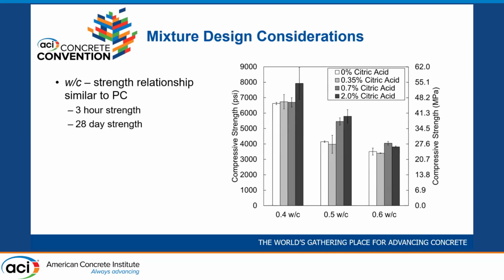And at 28 days, these are the strengths. So the strength continues to develop well on after 3 hours. And so you can see at a 0.4 water cement ratio, we're getting strengths up around 7,000 PSI. And the strengths are still quite good at higher water cement ratios.